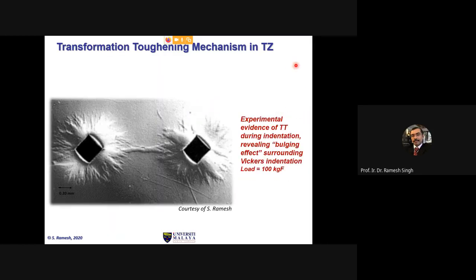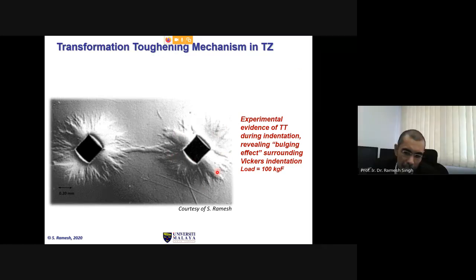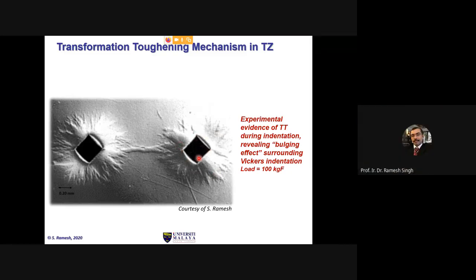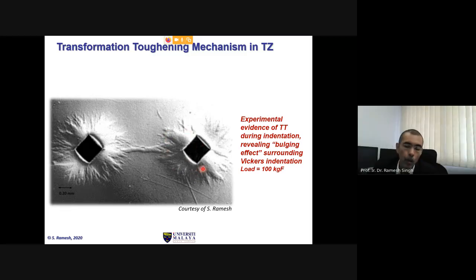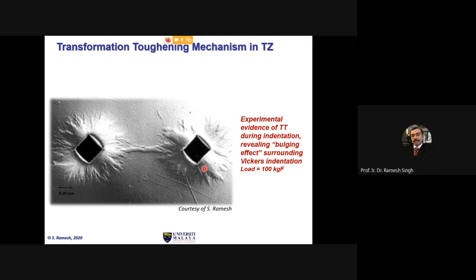So these are some evidences to show the bulging effect. As you can see, these are the transformation toughening effect. Normally, this is a typical Vickers indentation. You normally get cracks coming out from here, but in this case, you don't see cracks, right? You don't see cracks coming out from the corners, because you have the self-healing mechanism taking place, and you have this bulging effect. So what happens is that the crack cannot propagate, right? It gets shut, and you see the surfaces bulge, right? And this is the effect of crack arrest.